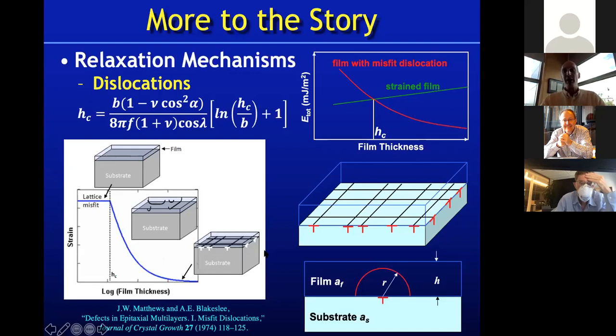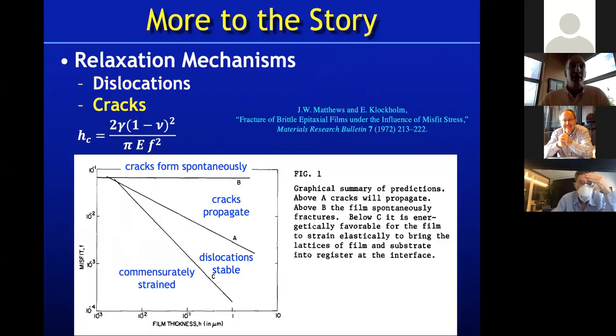Okay, so one of the realities is a finite thickness. So it's great to have huge strains. The bigger you make the strain, the thinner will be the critical thickness. So the strain is this F parameter down here. Okay, so they're inverse to each other. And I'll talk about what state of the art today is in terms of strain, but there's going to be a definite trade-off with how thick you can make that film as you go thicker. Typically 3% is about the maximum that can be done in perovskites. But there's another way that films can relax. They can crack. And again, this was calculated about 50 years ago by the same John Matthews.